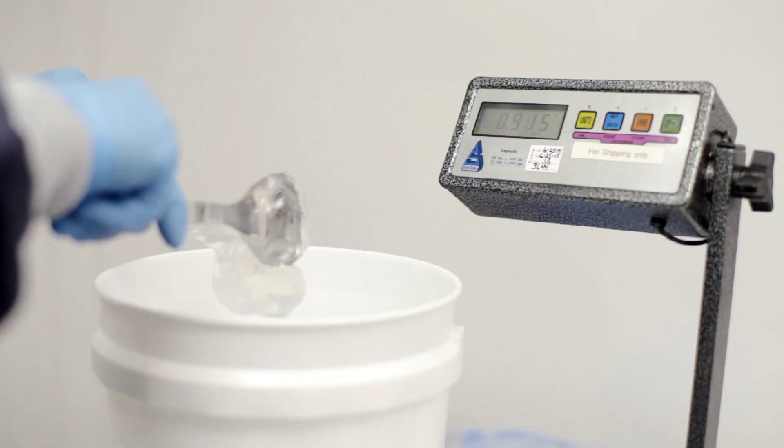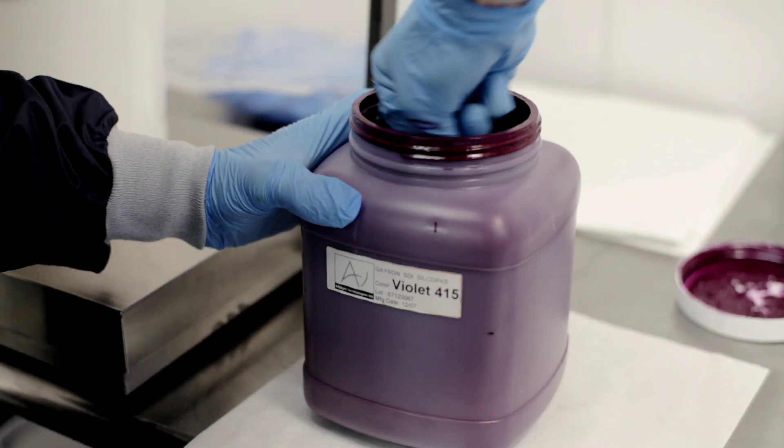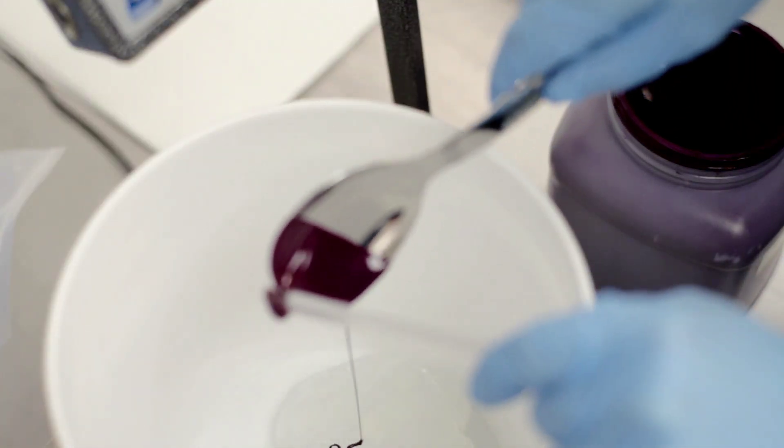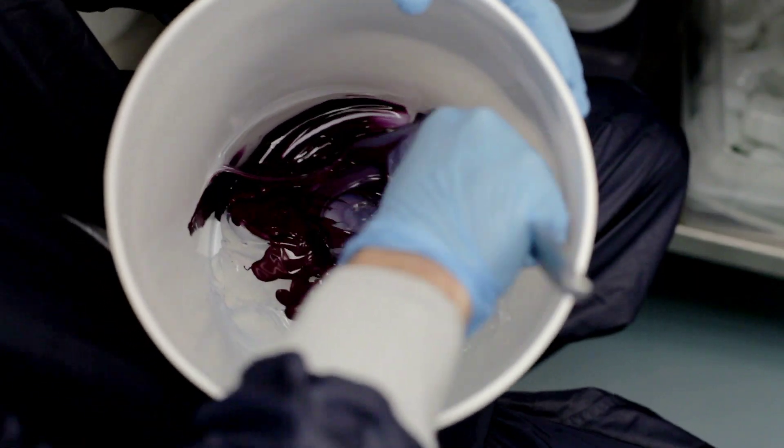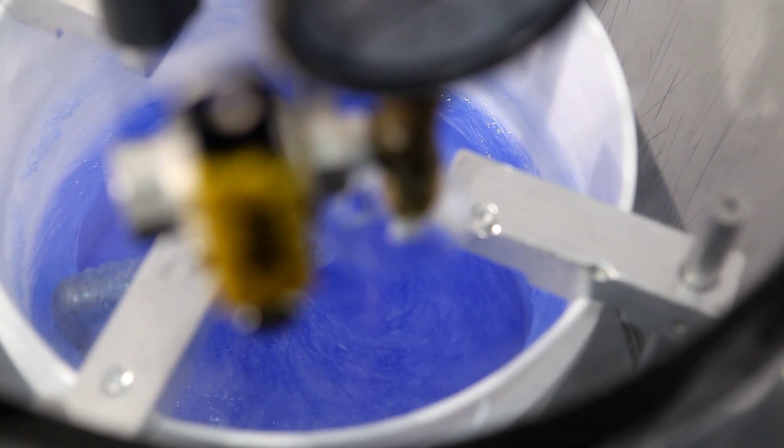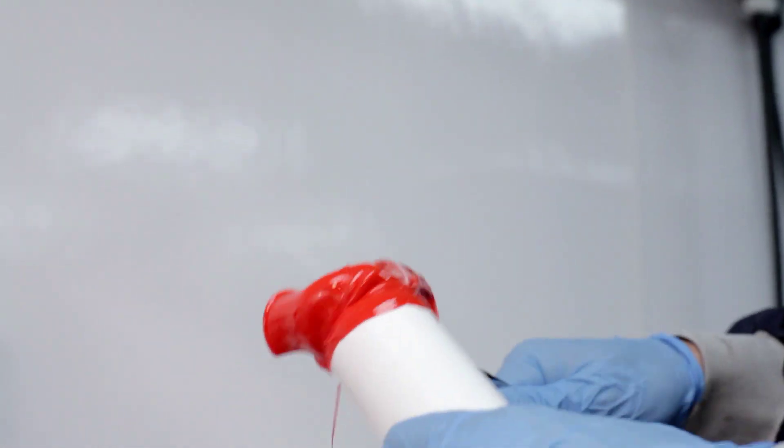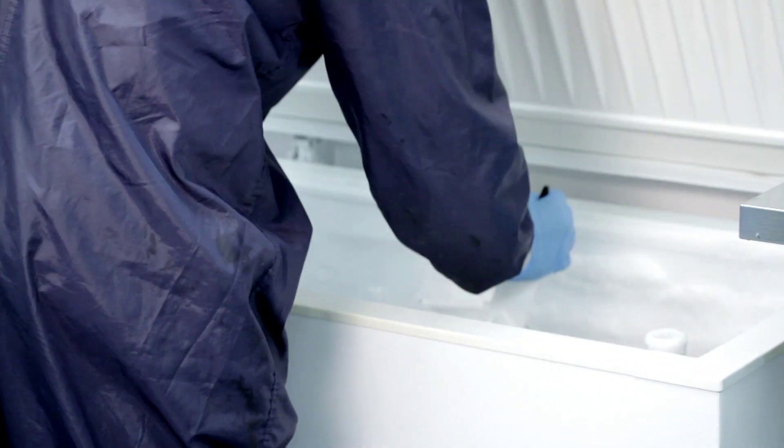We're showing an example of manual silicone mixing. Production silicone is created by a chemical reaction that starts with mixing a supplier's Part A and Part B. After mixing, the material is put in a freezer that will keep the silicone state uncured or unreacted for several weeks.